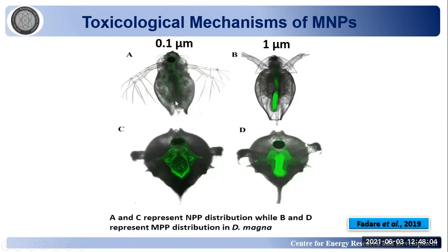So what you understand with the toxicity of Daphnia magna is physical toxicity. The hydrophobic nature of the particles weighs the animal down by sticking to the carapace, and as a result, the animal cannot feed, it cannot carry out normal metabolic activity, and that results in mortality.